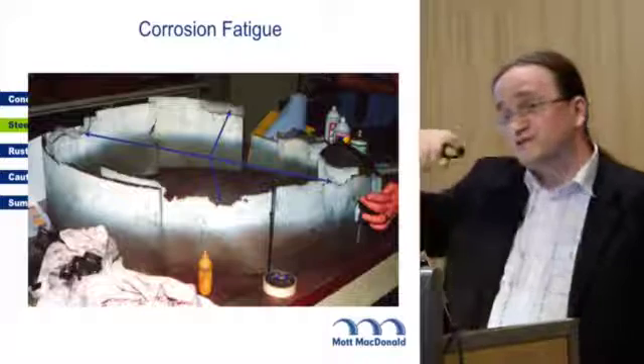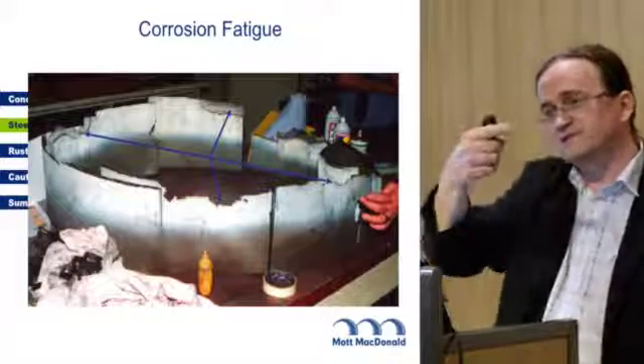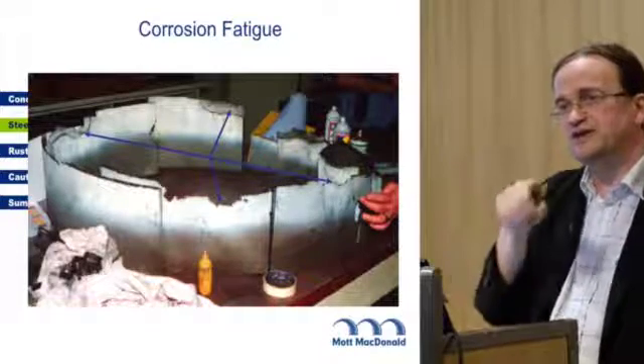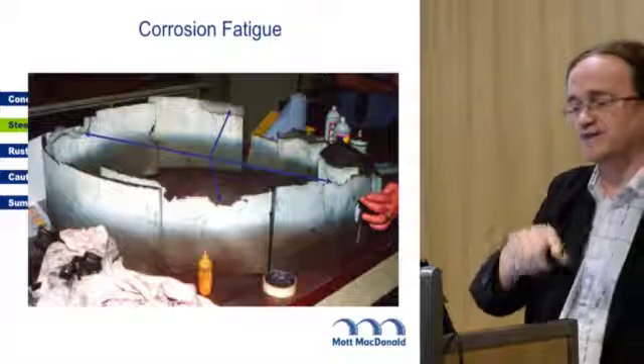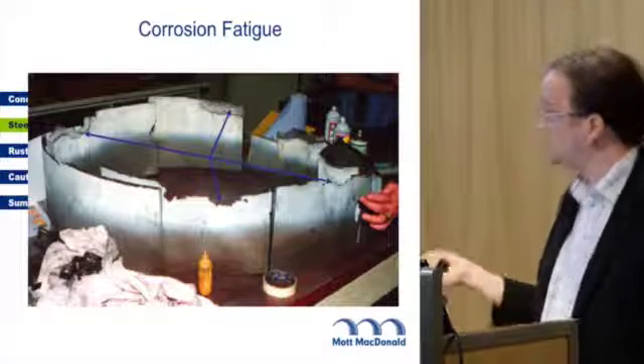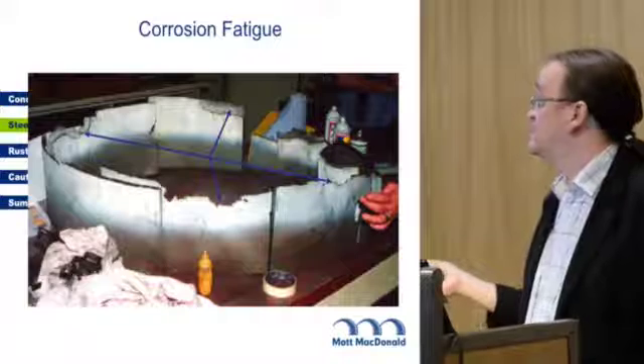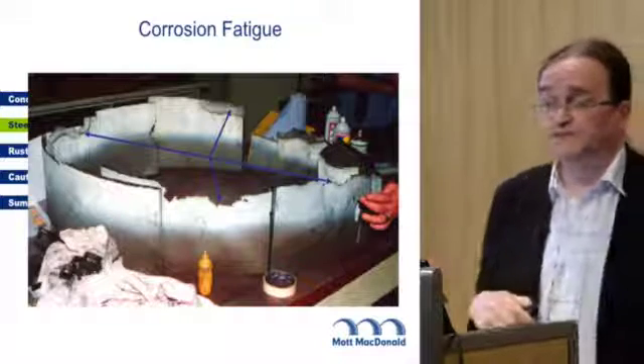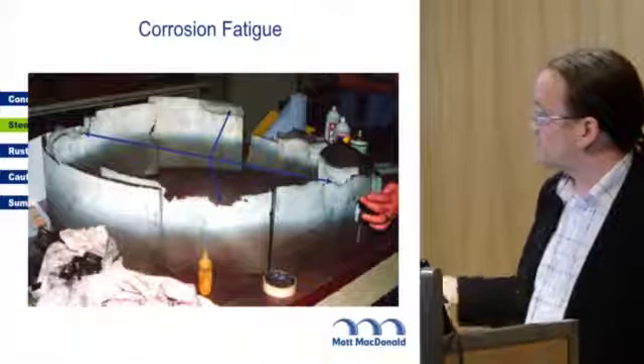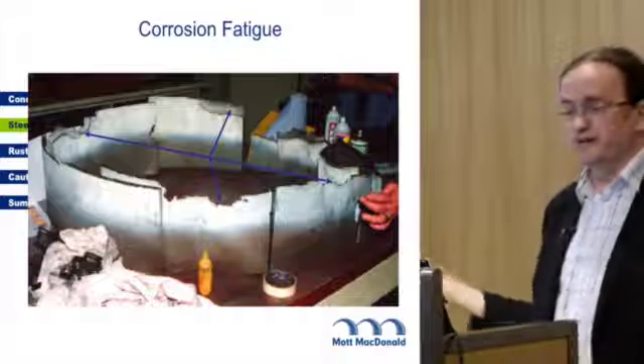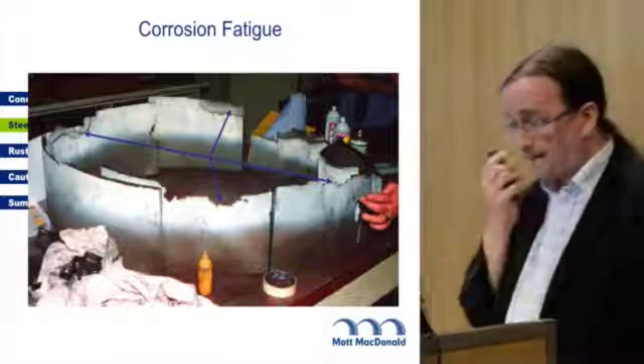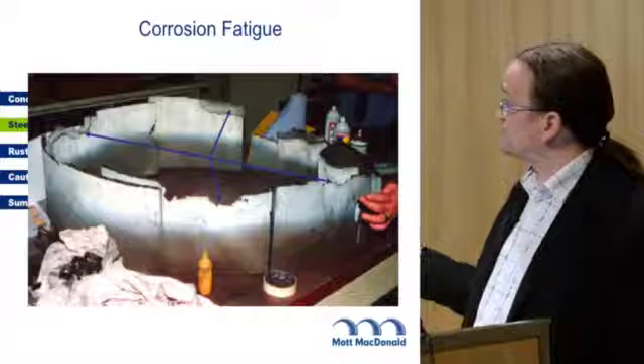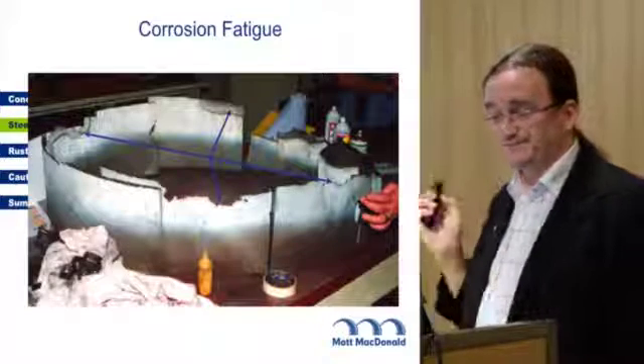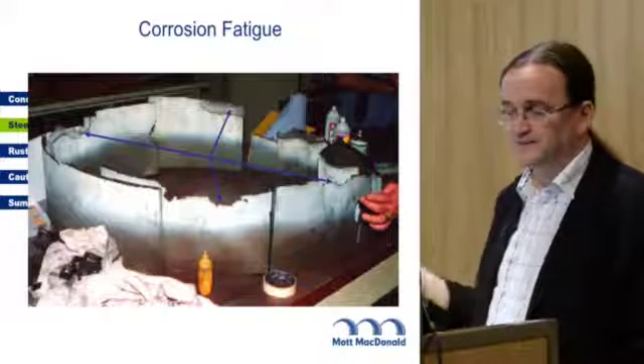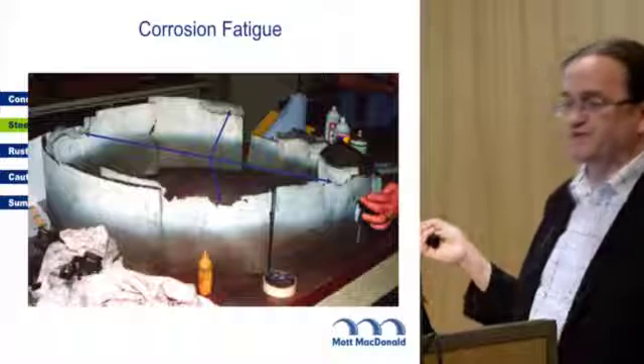But because corrosion gives you little notches and little holes and little ductility problems and little stress raisers, locally you end up sticking it over that stress. How do we deal with it? Coat it. Anything that we can do to deal with fatigue resistance also helps, so we can put the surface into compression by shot peening it or carburizing it or nitriding it. And that's an example of something that basically corrosion fatigued off. It's a fan casing, and that's where the failure happened before it ripped itself to pieces.